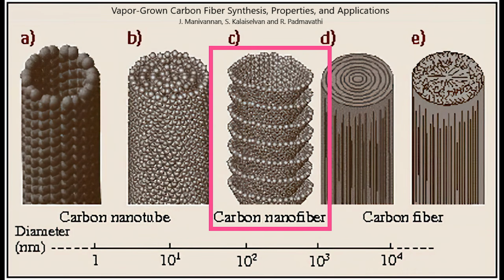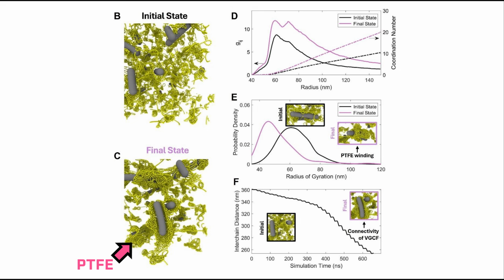How does the proposed solution actually work? When vapor-grown carbon fibers are used in the dry electrode process in place of carbon particles, the shear forces of the mixing cause the long PTFE filaments, shown here in yellow, to get twisted up around the carbon fibers, which are shown in black. Then the carbon fibers naturally form a chemical bond with the PTFE. That results in a binder-sheathed carbon fiber that's insulated from reacting with the electrolyte. It's not completely insulated because the binder doesn't perfectly cover the carbon, but as we'll see in a moment, it helps tremendously.